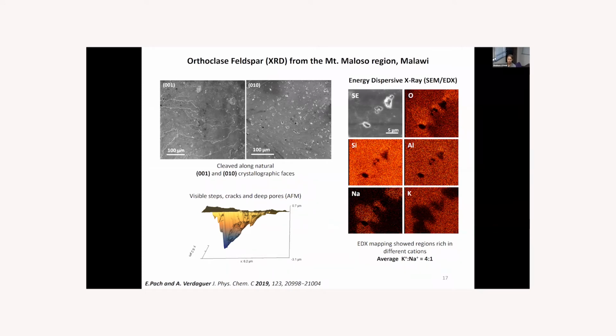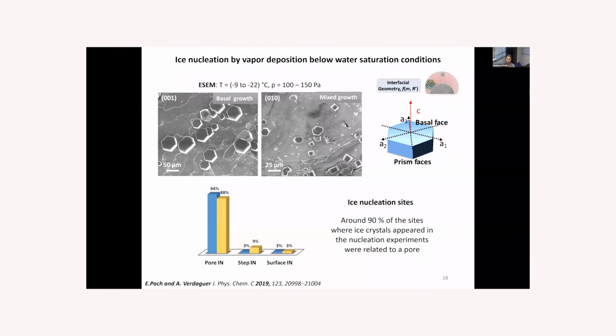This may be important for the studies of ice nucleation. Some people were saying that this is probably where the nucleation should occur. So we have performed the experiments at the ESEM, varying temperature from -9 to -22. And by varying the pressure of 100 to 150 pascals, we created different relative humidity conditions up to 100%. And we could observe, as I already told you, the preferential growth on different faces. But the most important result from this was that we calculated that around 90% of all the sites where ice crystals appeared in the nucleation experiments were related to a pore. And only a small amount of them were related to a step or the surface.